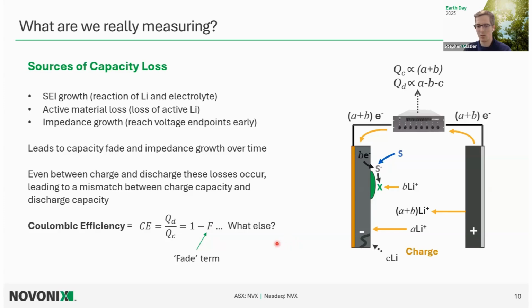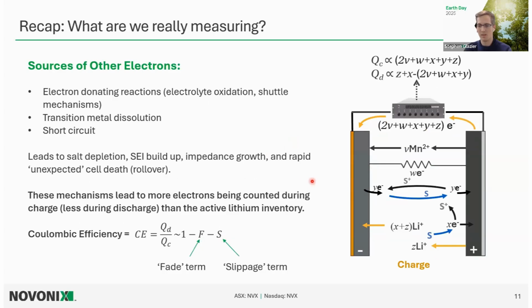And now we're going to build this out even further. So what else contributes to electrons being counted through this external circuit when we're testing a cell? And this is where things get a lot more exciting in the diagram. We have a lot more different types of mechanisms that can happen. And so what can contribute electrons? Definitely electron donating reactions, things like electrolyte oxidation, shuttle mechanisms, transition metal dissolution, short circuits or self-discharge within a cell. And all of these things lead to salt depletion, SEI buildup, impedance growth. And these are kind of the silent killers that lead to rollover failure, a lot of the times unexpectedly.